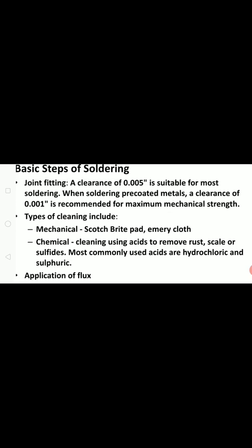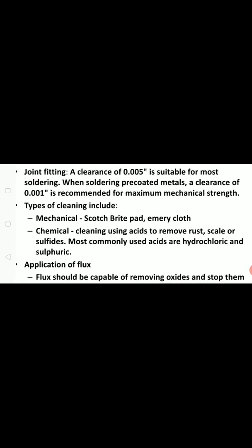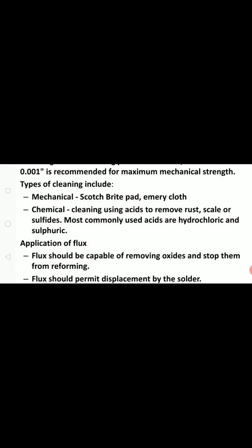Next, cleaning has to be carried out. We have already said this. The surfaces should not contain oil, wax, lint, any other particles, or dust. These should be removed either by mechanical or chemical means. A Scotch-Brite pad or emery cloth is normally employed mechanically. Chemical cleaning means cleaning using acids to remove rust, scale or sulfides. The most commonly used acids are hydrochloric or sulfuric acid, used to clean the work part.